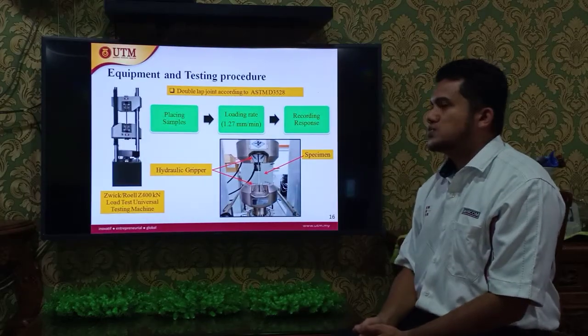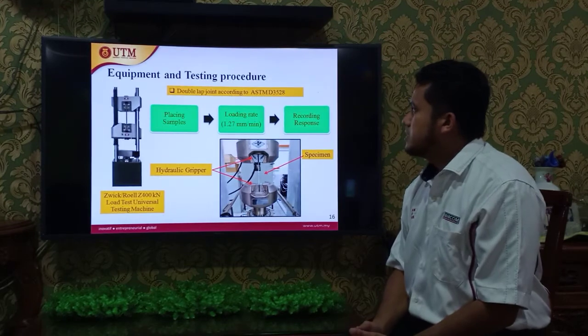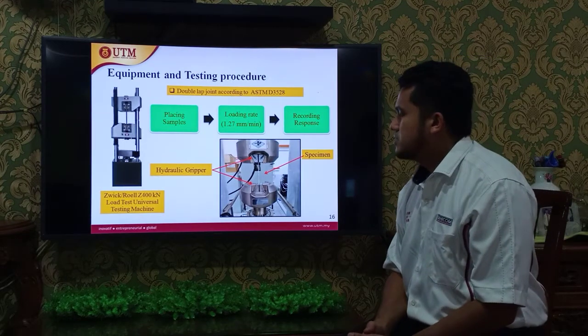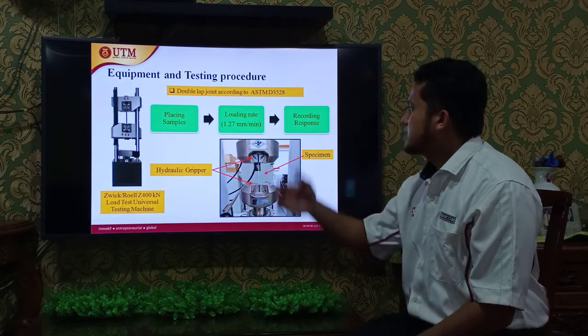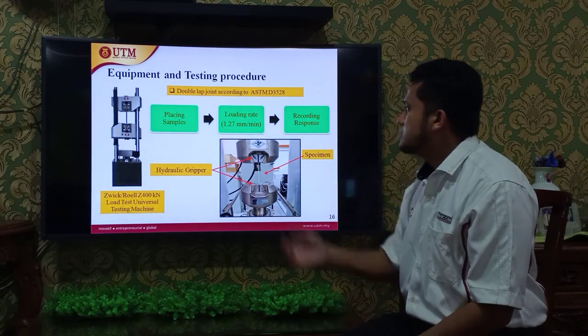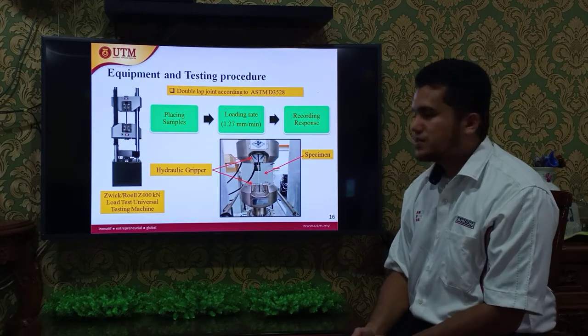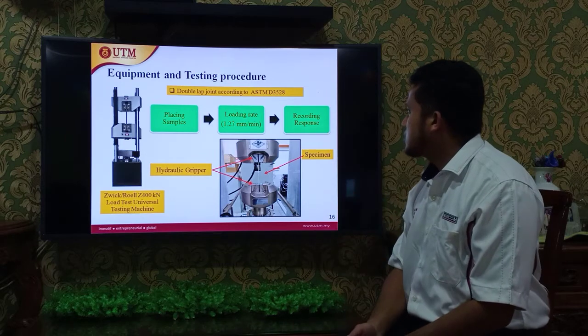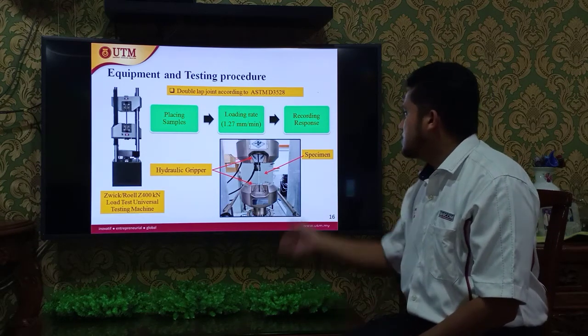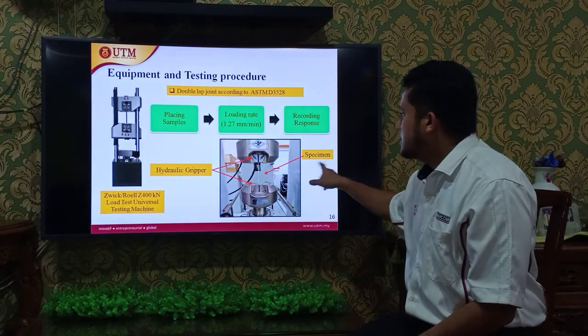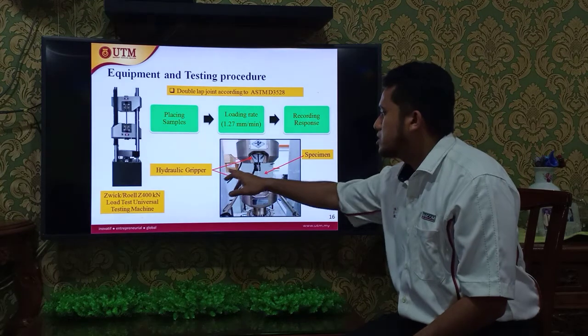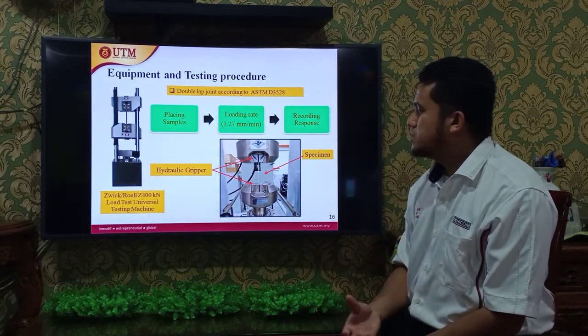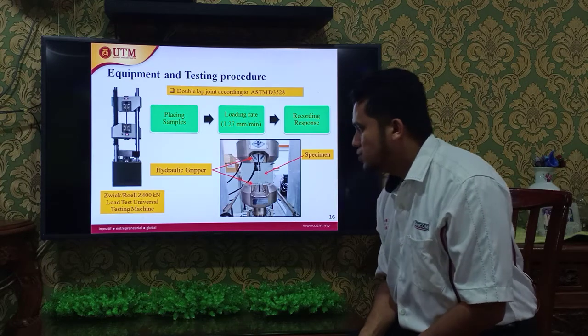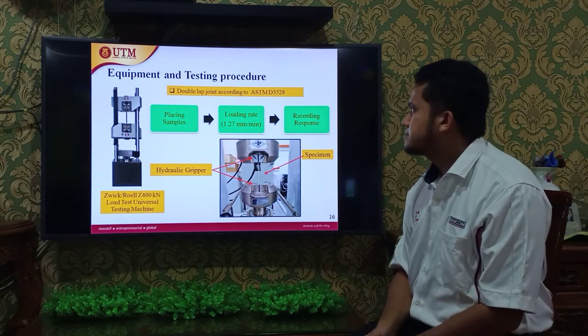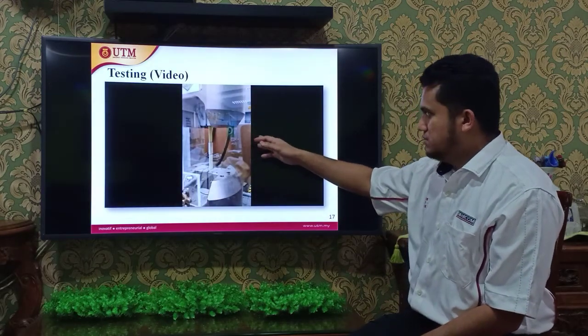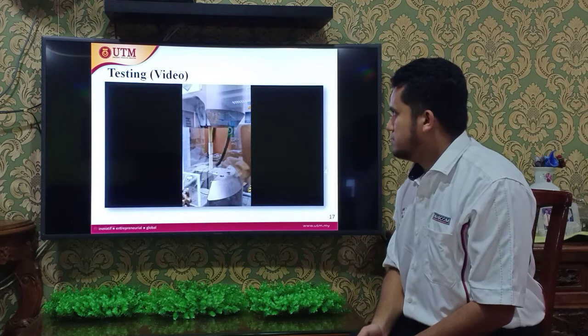This is the equipment and testing procedure. We do the double lap joint test according to ASTM D3528. First, placing the samples. Second, we use a loading rate of 1.27 mm per minute. And lastly, the recording, where we get the result. This is the test picture of the specimen, with the upper and lower hydraulic grippers. We do the load test on the universal testing machine Zwick Z400 kN. This is the video for the testing process.